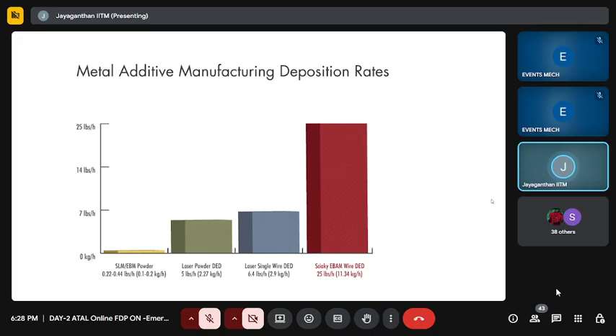If the feature size is of the order of millimeter, we can always go for a machine which can ensure a very high deposition rate. It is like saying one printer cannot be used for printing any size and shape of the component. That's where there are three different variants of 3D printers. Principles are the same. We are using either a thin layer of powder or wire, scanning it with a laser, and it undergoes controlled solidification. But again, the way you use the process variables is going to dictate the kind of dimension, size and shape of the component you are going to achieve.